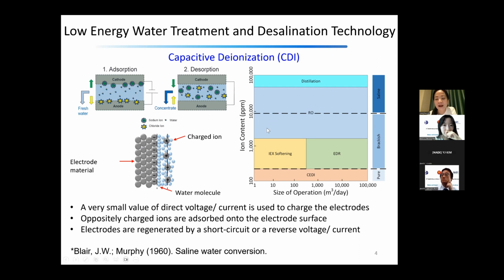And we can see over here, there are different salty levels of ion concentration. For example, from 100 ppm to 1000 ppm, from 1000 ppm to 10,000 ppm, and then from 10,000 ppm to 100,000 ppm. From these different domains, we can see that the thermal method will be very suitable for water with a concentration from 80,000 to 100,000 or above 100,000 ppm. And then RO, reverse osmosis membrane technology, will be very suitable for water from around 2,000 ppm to around 80,000 ppm. And then for EDR or IEX softening, those methods will be very suitable for brackish water treatment, which will be from a few hundred ppm to 1,000 ppm.